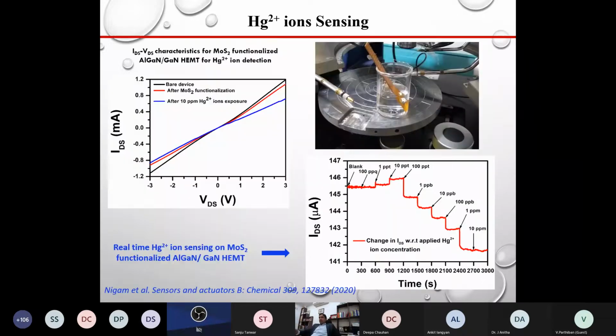Next, we have to measure how much current flows. So we put this inside the water and measured the current-voltage characteristics. This is for the bare device. After transferring MoS2, the current has reduced, and when we put mercury ions in this case, the current started decreasing. And if we apply a constant voltage between source and drain and monitor the current, what is happening?